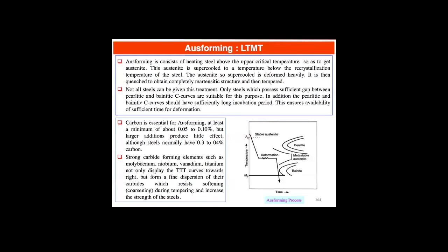Grain growth and coarsening of the particles, right? You've got a lot more time to work here, provided the nose of the bainite curve isn't too far forward, but we generally have enough alloying elements that we're not going to be worried about this. So again, at the workshop, there was a lot of debate about, for different steels, whether it would be best to process by the aus-forming route or by controlled rolling.